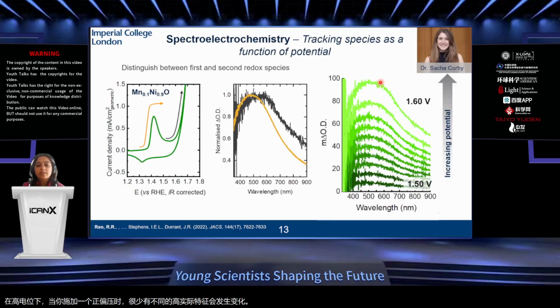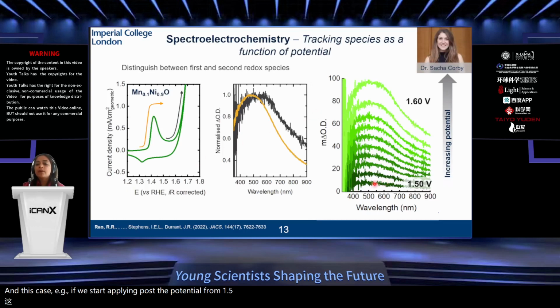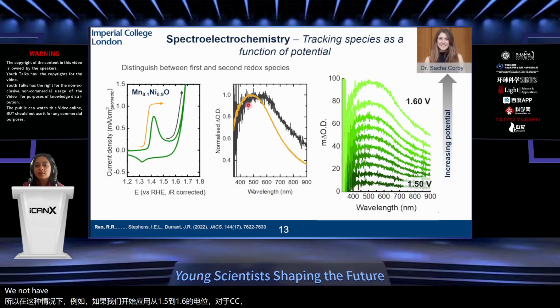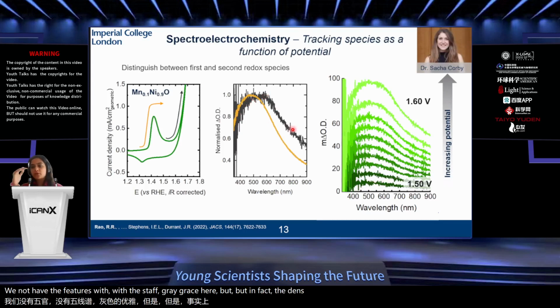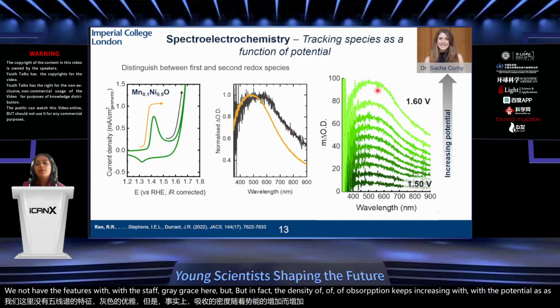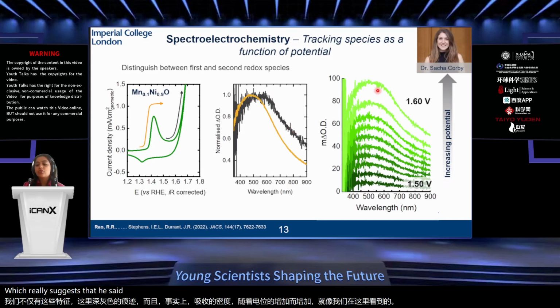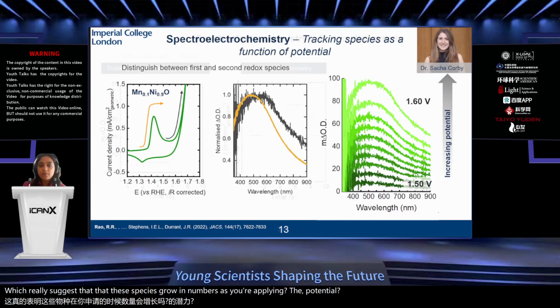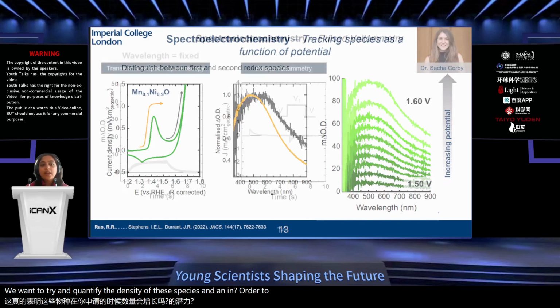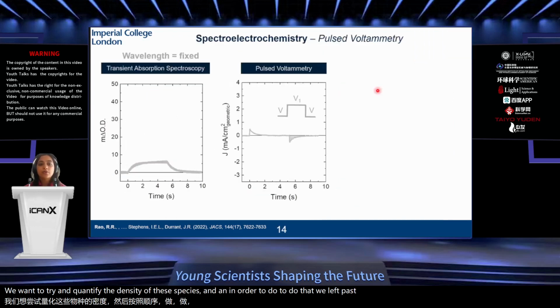So in this case, for example, if we start applying positive potential from 1.5 going up to 1.6 volts, we not only have these features with this dark gray trace here, but in fact, the density of absorption keeps increasing with the potential, as we can see here, which really suggests that these species grow in number as you're applying the potential. We want to try and quantify the density of these species, and in order to do that, we look at transient absorption spectroscopy.